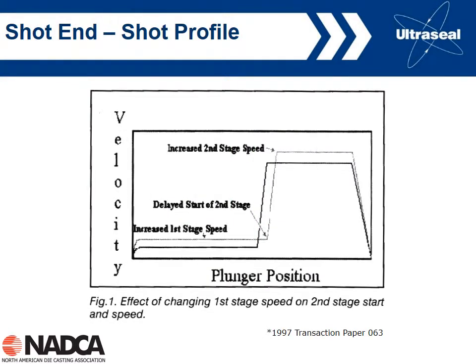So if we look in a bit more detail at the actual shot profile, this is obviously a traditional shot profile. The die filling time is essentially the fast part, the second stage, shown here. So the time to fill the cavity is basically the time from the start of the fast shot to the end of the profile. Obviously the slow shot velocity is also very important, certainly in cold chamber, where we're controlling the wave formation in the shot sleeve, because we need to minimize the amount of air trapped as we fill the sleeve.